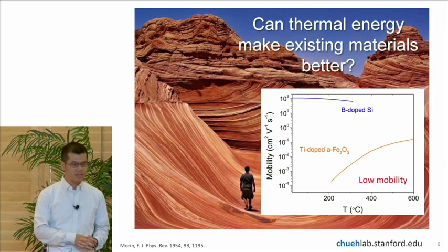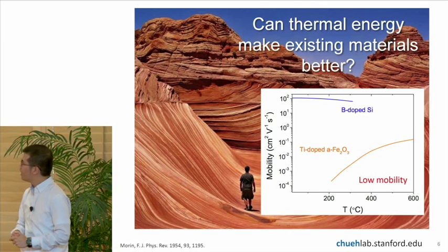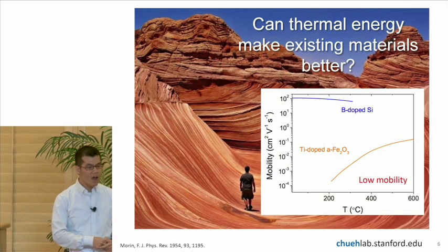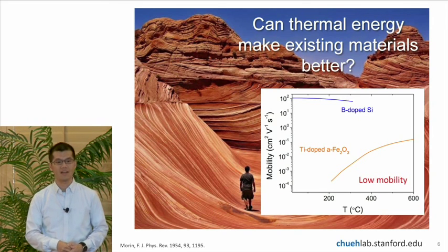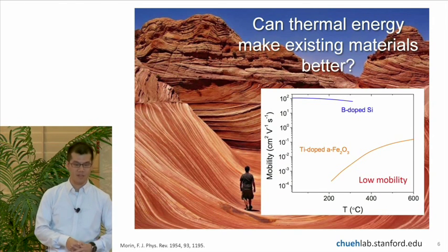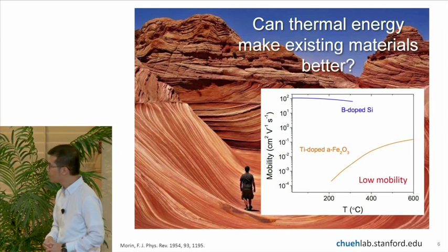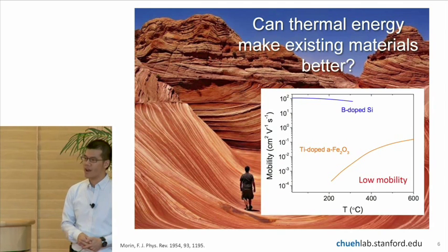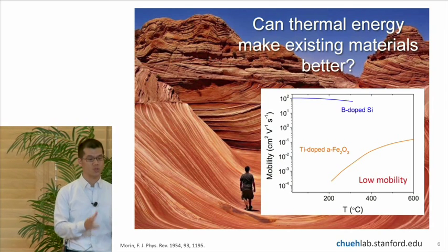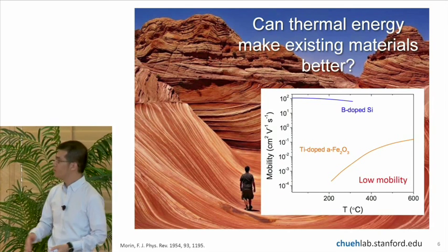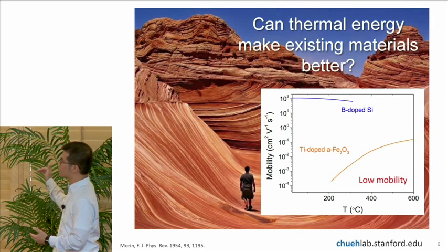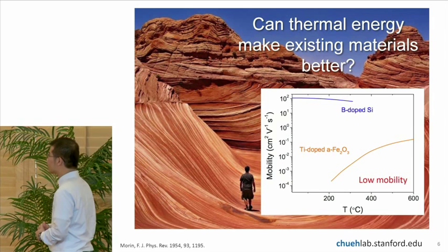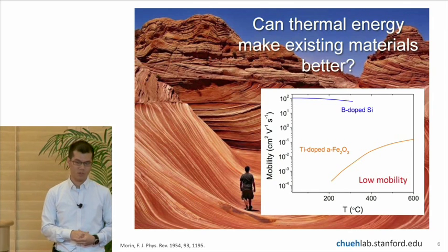So here I show you a plot of the mobility of silicon and the iron oxide as a function of temperature. And you can see silicon's way up there, it's about ten to the two centimeters squared per volt per second. And iron oxide actually has mobility that is immeasurable at room temperature because it's so lousy. But what you can see, a very significant contrast between the two material, it is the slope on temperature. So while silicon decreases slightly in mobility when you increase the temperature,